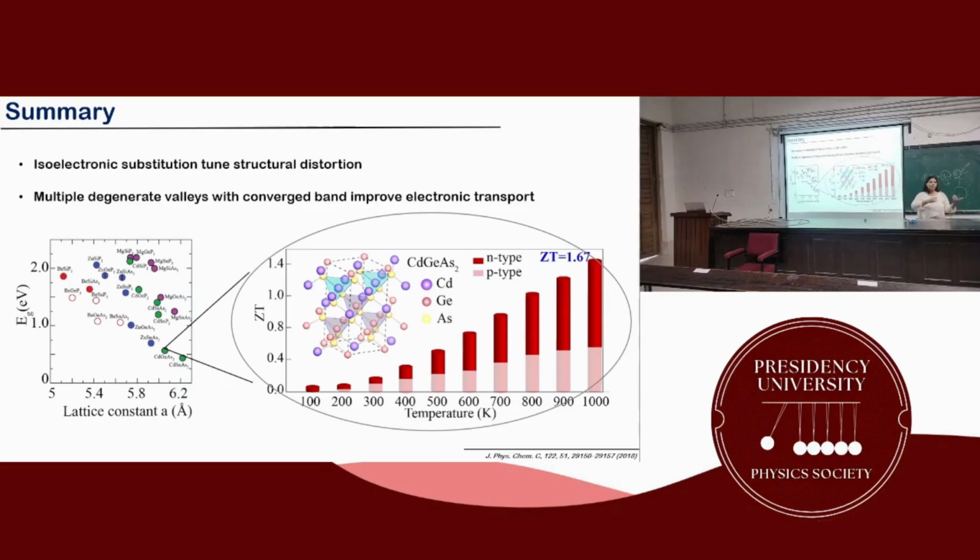And then you feed it into the Boltzmann transport equation, and the same for the phonon. The phonon is typically a temperature dependent effect, because without temperature, how would the vibration come? But here what we do is basically a harmonic approximation, or some kind of small displacement calculation, where we are confident that on my potential energy surface, the atoms will move only around the equilibrium position, but not far from it. Within this limitation, our DFT works fine.